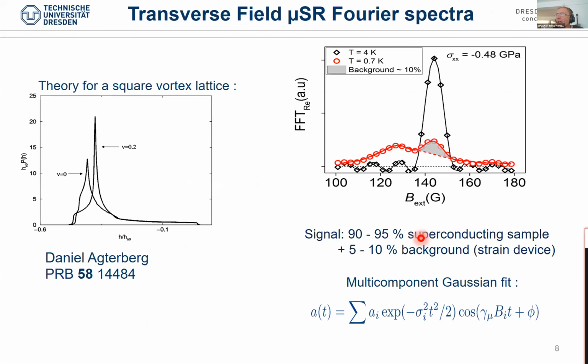And to check that we really have a good signal from the sample, we can do transverse field μSR, because in the transverse field, you expect to see the vortex lattice state, and there are predictions from many years ago by Daniel Agterberg that you would see this characteristic distribution of internal fields in the superconducting state. And here on the right side, you see one of these experiments.